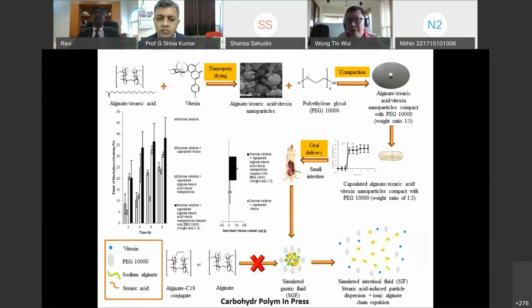Now, what we have found out is that the polyethylene glycol functions very well to reduce the vitexin release to almost 0% in the gastric region. Upon the compact entering the intestinal region, you can see a surge in drug release. So the small molecule vitexin is very hard to control, right? But in our case, we are able to reduce the release in the gastric phase to 0% and enhance the release in the intestinal region.